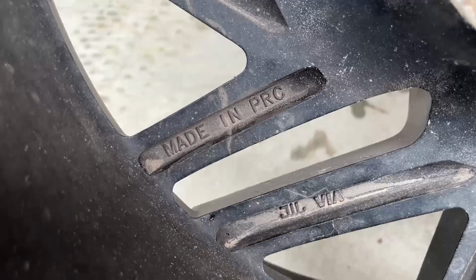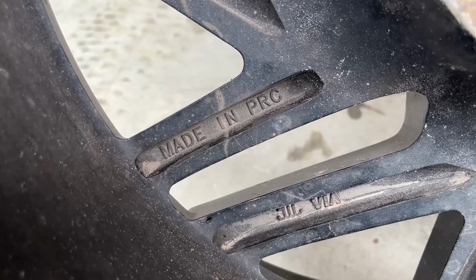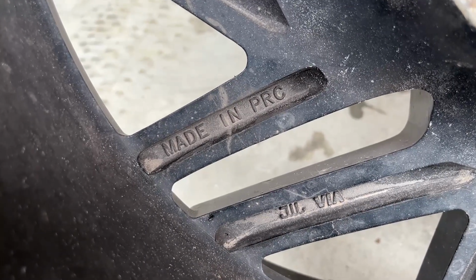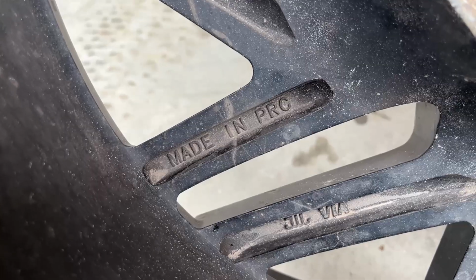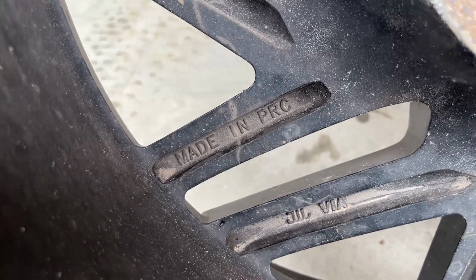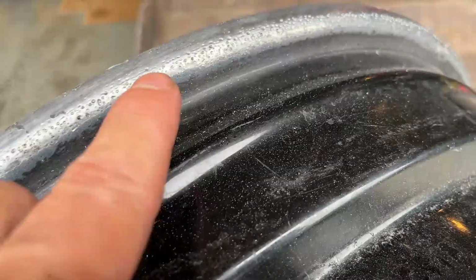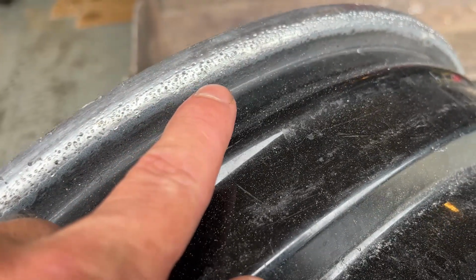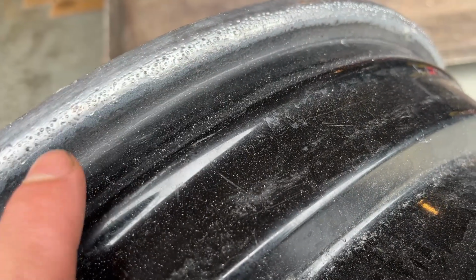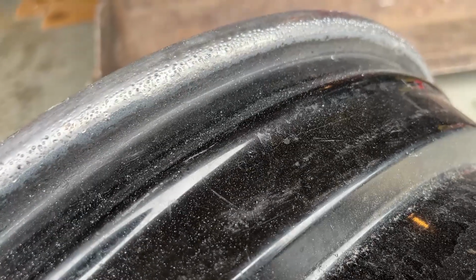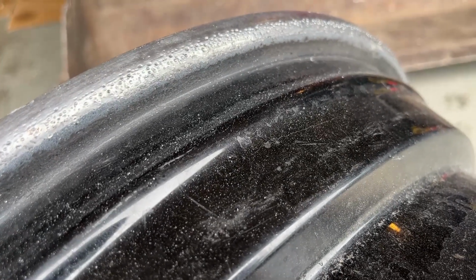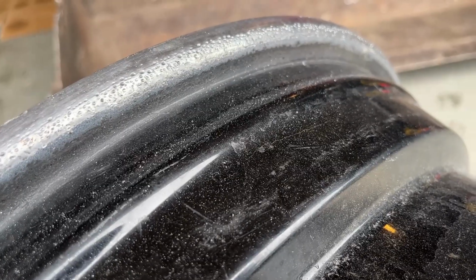Upon further inspection, I'm convinced this is probably an A356, right? But it's definitely a casting, and one of the clues upon further inspection here is that I'm critiquing my own weld as I'm sanding it off. I'm looking at the inherent porosity in this casting. So expect when you weld on cast aluminum for it to bubble up at you. It's just its way of showing some love.